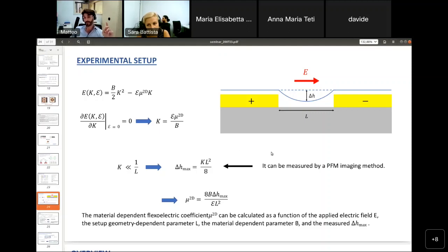In the small curvature regime, compared with the parameter L, which is a geometrical parameter of the setup considered, we can also extract the maximum bending distance. Such a bending of the material can be measured by use of the so-called piezoresponse force microscopy, and then we can take an image of the sample. By use of the applied electric field, the geometrical parameter L described in the setup, and the measured curvature, we can hypothetically extract the flexoelectric response that we defined and described in the article.